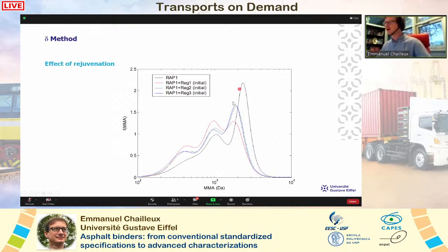overall distribution. And when we add regenerator, so in this case 3 regenerator was used, we see that this big molecular structure is destroyed in favor of another intermediate molecular structure, and we see that another population appear here in the lower mass domain, which is linked to the regenerator itself, which is a very low viscosity material.